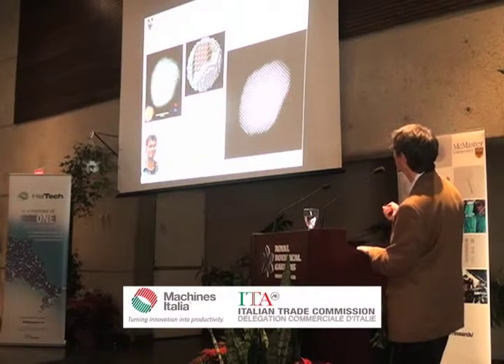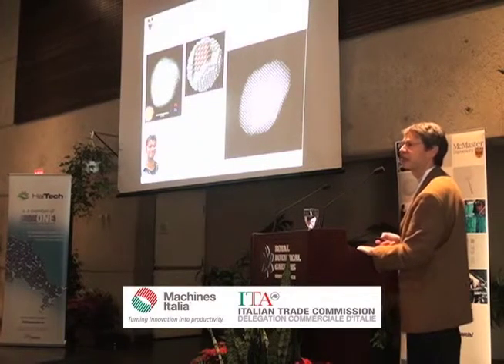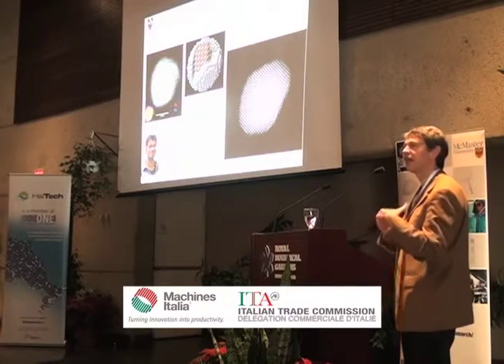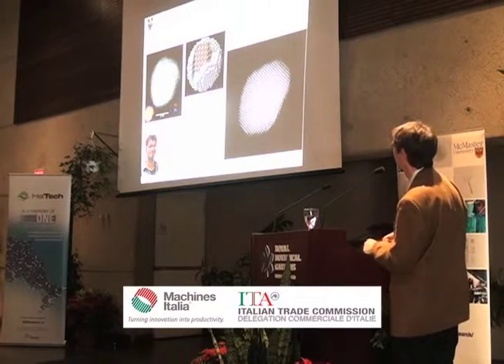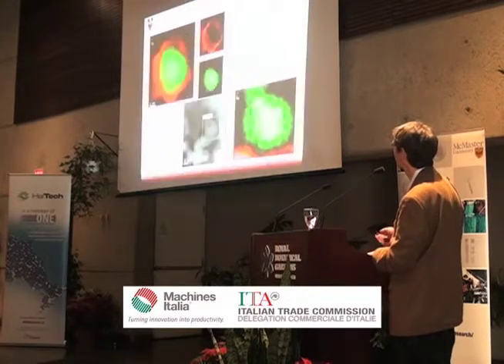These images also provide an idea of the exact shape of the particle. You can see there some planes of atoms that are incomplete, so they are surface steps. And this is very useful for the chemist to know that you have the surface steps because they can tell then what are the sites that actually promote the breaking down of hydrogen and oxygen molecules when you operate in a fuel cell. So we provide this kind of information if not obtained other ways.